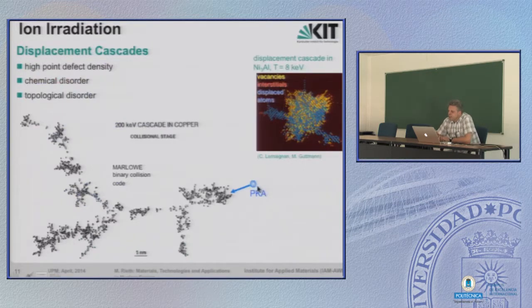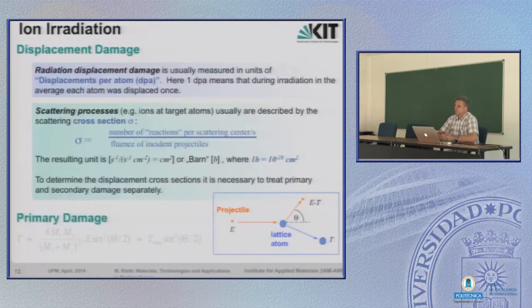This is what it looks like if we have a primary knock-on atom. It leaves a series of secondary damage behind it. So it produces a rather high point defect density. It produces chemical disorder because all the atoms are moved, and also a topological disorder. The lattice is in many places destroyed or dissolved. To account for all these damages or displacements, which we call displacement damage, you need a separate measure. And this radiation displacement damage is usually measured in units of dpa, simply displacements per atom.